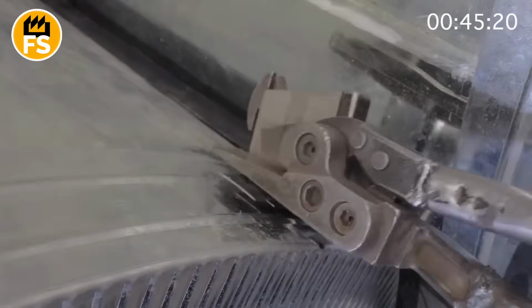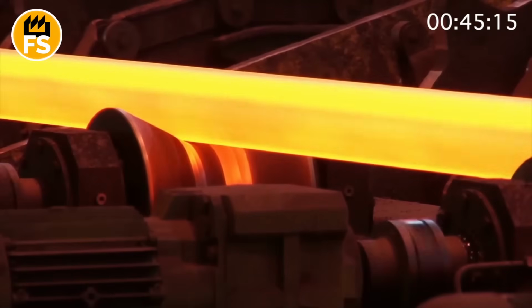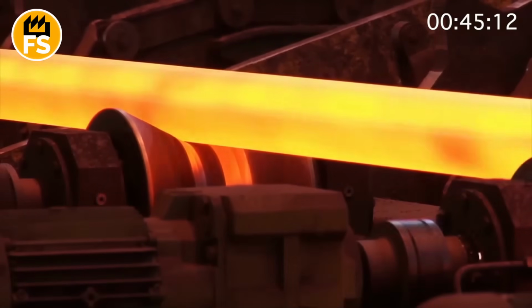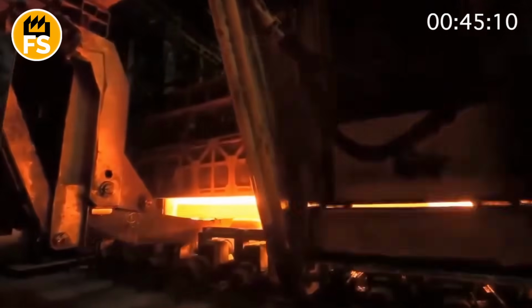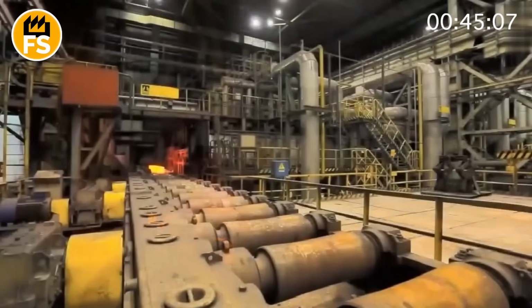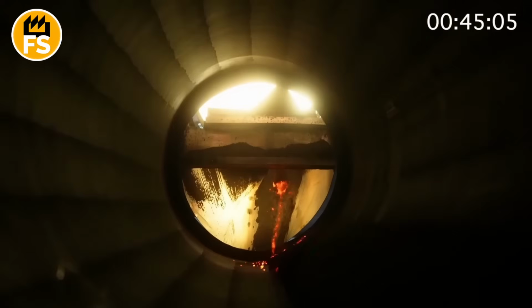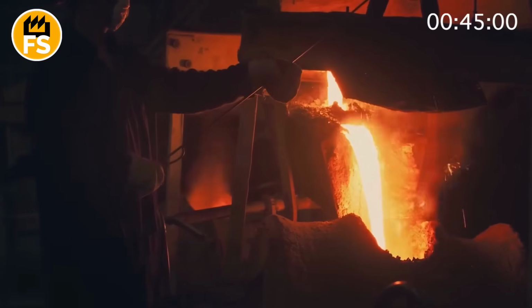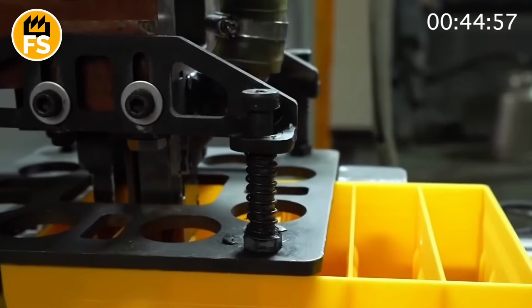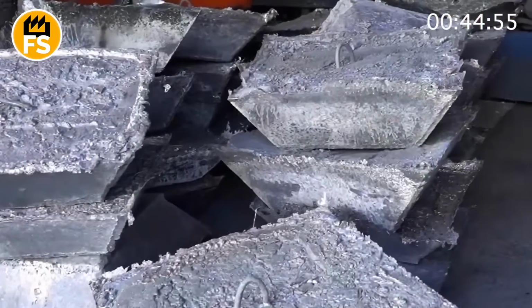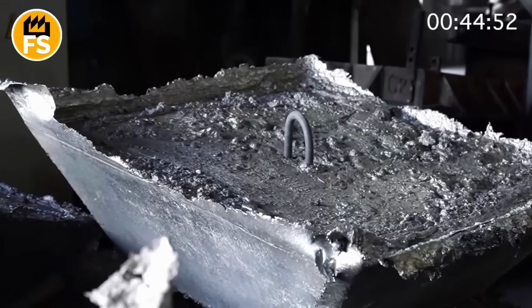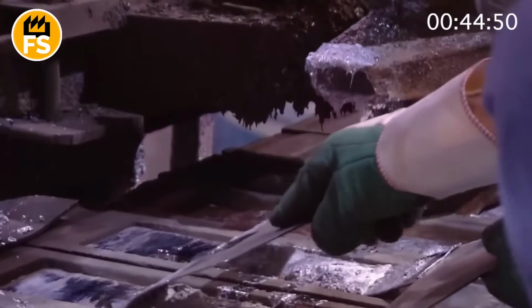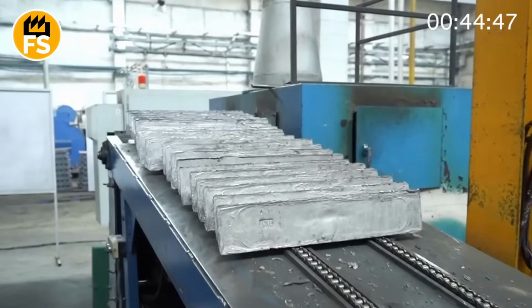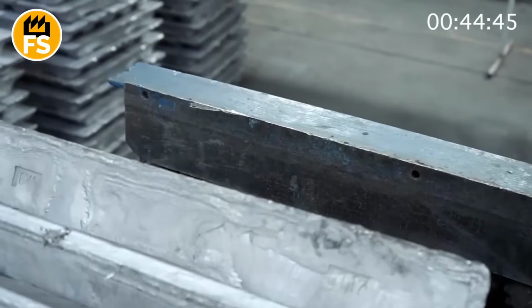Blanks for shells are made at steel mills, where the metal is melted in large furnaces at temperatures exceeding 2,700 degrees Fahrenheit. After this, the molten metal is poured into molds, resulting in large plates or rectangular blocks. Then these plates are rolled on rolling mills, reducing the thickness to the required parameters, 2 inches and less. Rolling mills can be either hot or cold, depending on the processing stage. Hot rolled sheets have lower accuracy, but are easily formed, while cold rolled sheets are ideal for parts requiring high precision and a smooth surface finish.